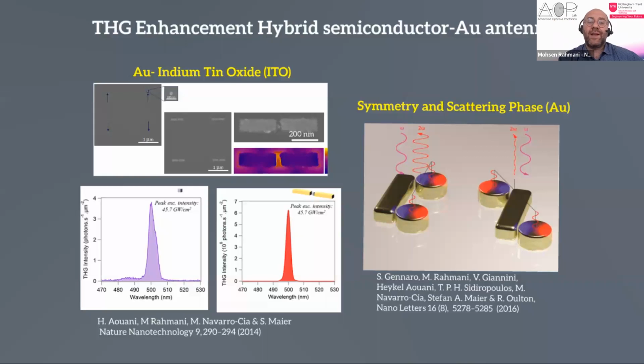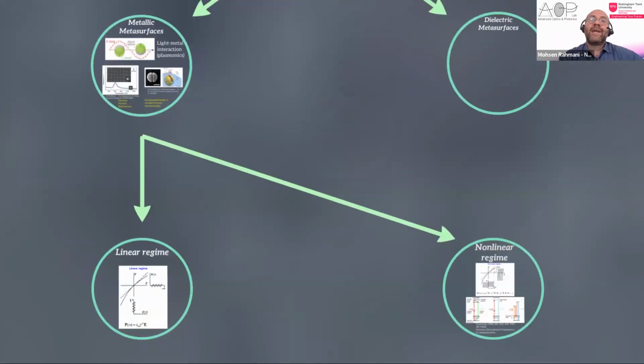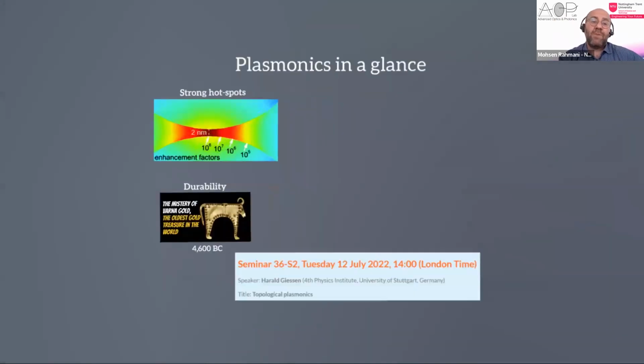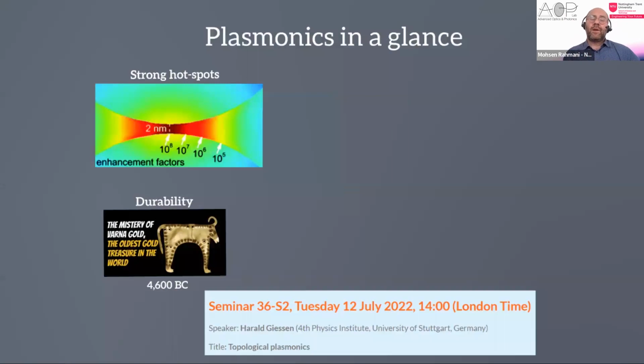So that's why this issue and other issues made people think that probably they have to migrate to some other material. Despite the very nice properties of metals, and in particular plasmonics, including a strong hotspot and durability, I have to emphasize this durability, because the good thing about plasmonic nanostructures is that they can be used for many years. I can still use the plasmonic nanostructures which I made at the beginning of my PhD in 2009. They still work perfectly fine. They do not oxidize, in particular gold. Of course, it is not the case for silver, but gold does not oxidize, nothing happens to it, so you can use it for years and years.